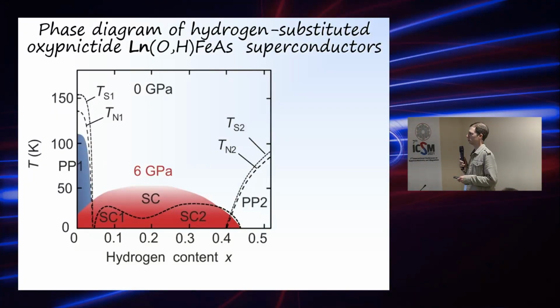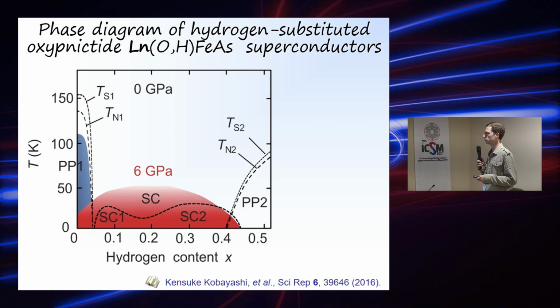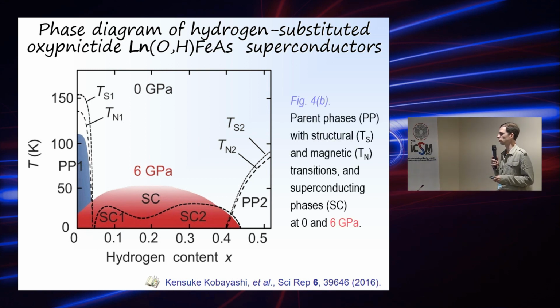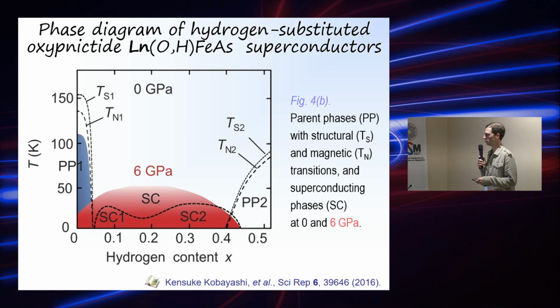But in comparison to other 1111 compounds, this hydrogen substitution gives a very unusual phase diagram. For the 1 atmosphere pressure, you should see only the black lines, not the colored ones. It is taken from this very nice work of Kobayashi et al. You could see that the superconducting phase develops between the two parent phases, and near the edge of the magnetic and structural transitions, superconductivity develops. But it's very unusual for hydrogen doping because you see two domes here.